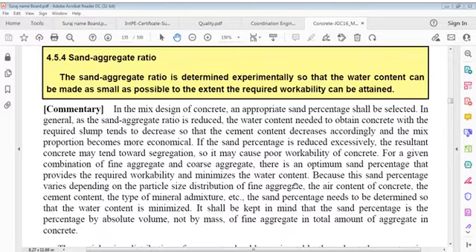In mix design of concrete, an appropriate sand percentage shall be selected. As the sand aggregate ratio is reduced, the water content needed to obtain concrete with the required slump tends to decrease, so that cement content decreases accordingly and mix proportions become more economical. If the sand percentage is reduced excessively, the resultant concrete may tend towards segregation,